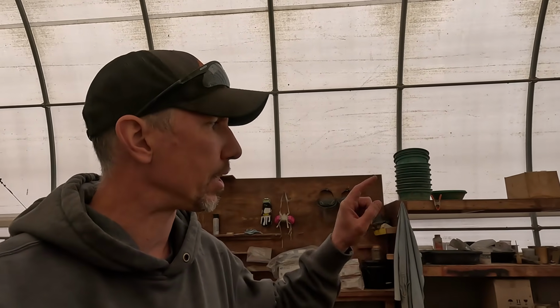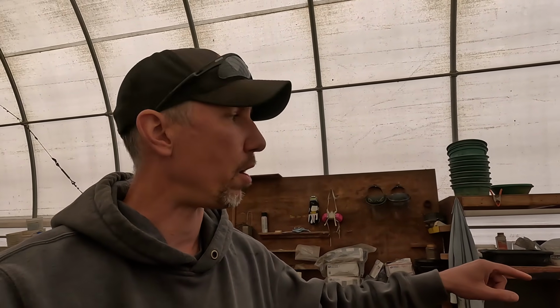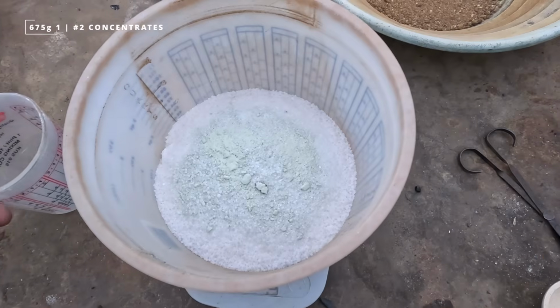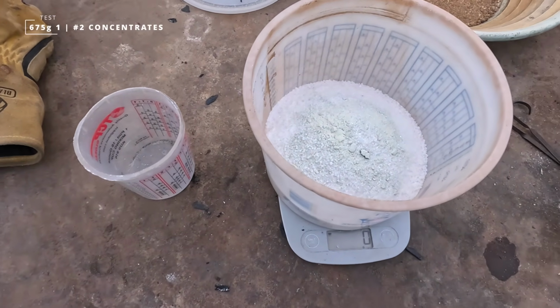So I'm gonna mix up another smelt. I'm gonna try and get them down to 2 smelts. So I'll probably do about 675 grams of ore concentrates, smelt it down, do the next one, combine both beads into our cupel, and cupel away and see if we can get our roughly 3 grams of gold, 2 grams of gold, somewhere in there. Somewhere in the middle of that, I will check on that bead that's in the cupel now, and we'll see about our number 3 cons. All right, here it is. We'll shake it up and get it in the furnace.